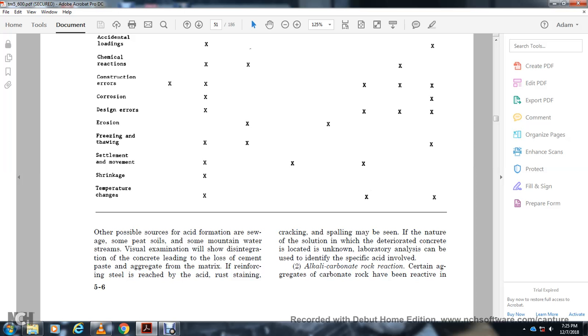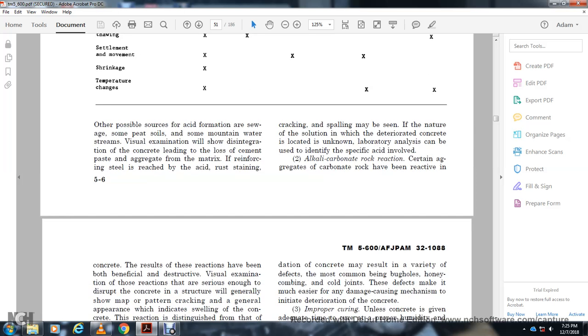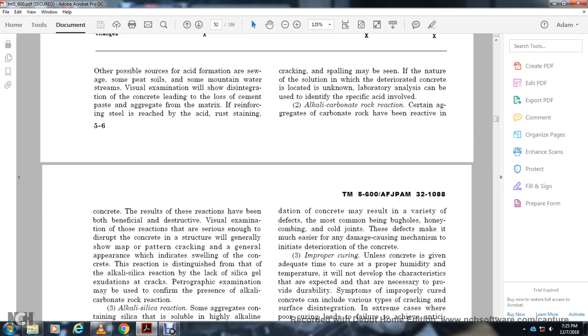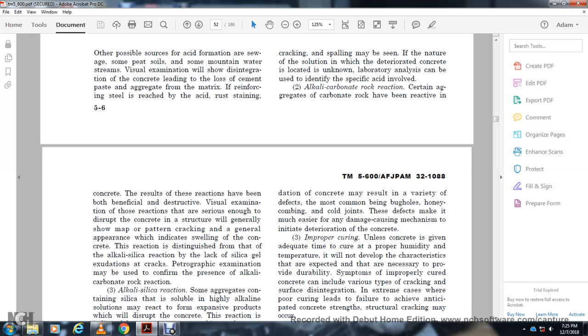Alkali carbonate rock reaction. This concerns aggregate of carbonate rock that is reactive in the concrete. A visual examination of the reaction shows enough swelling to disrupt the concrete, with a map pattern of cracking. The general appearance of the swelling of the concrete distinguishes it from alkali silica reaction, with a lack of silica gel exudates at cracks. Petrographic examination may be used to confirm the presence of the alkali carbonate rock reaction.